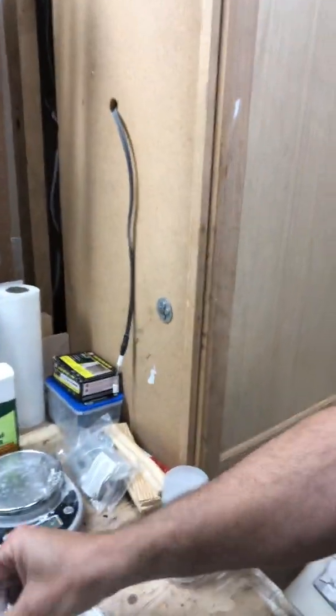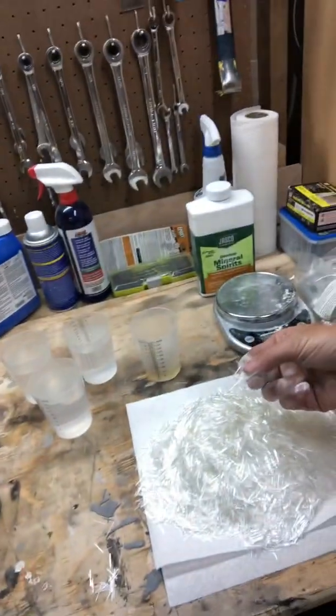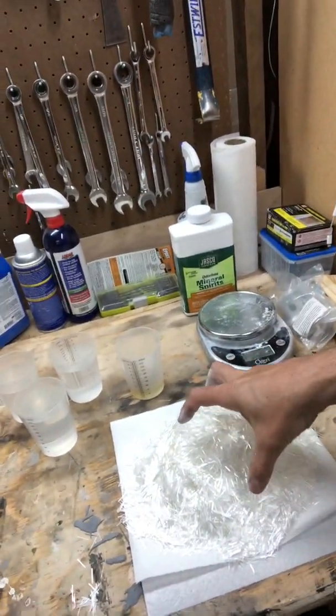And then I will add this stuff. Now these are glass fibers, and it's 1/3 pound of glass fibers, and I'll add that to the mix and pour that in, and that's the backing layer, and that actually gives you the strength. If I just did this stuff with the water reducer, it would be okay, but it wouldn't survive the test of time. You couldn't do a drop test on it. But once you put this stuff in there, holy buckets, just rock solid.